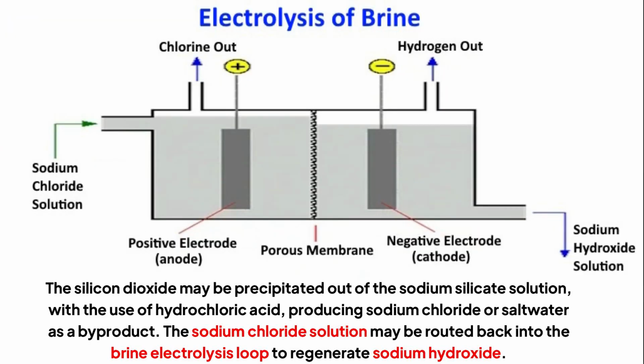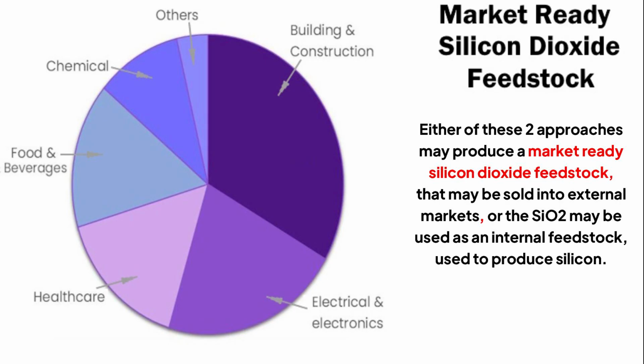The silicon dioxide may be precipitated out of the sodium silicate solution, with the use of hydrochloric acid, producing sodium chloride or salt water as a byproduct. The sodium chloride solution may be routed back into the brine electrolysis loop to regenerate sodium hydroxide. Either of these two approaches may produce a market-ready silicon dioxide feedstock that may be sold into external markets, or the SiO2 may be used as an internal feedstock, used to produce silicon.